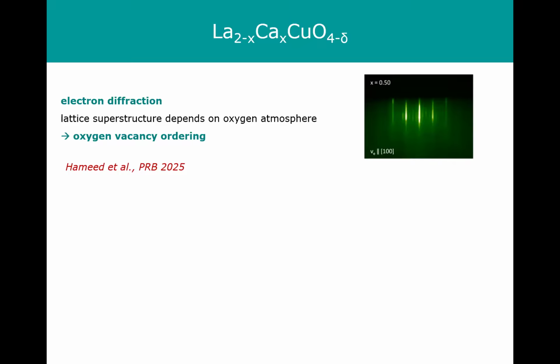And well, one thing that we can do in our thin film machine is to just change the oxygen content at which these films are grown. And it turns out, while the films are grown, we actually see in the RHEED pattern a superstructure that we can change by changing the oxygen content. So this implies that it's really an oxygen superstructure, specifically an oxygen vacancy ordering that we're seeing here.